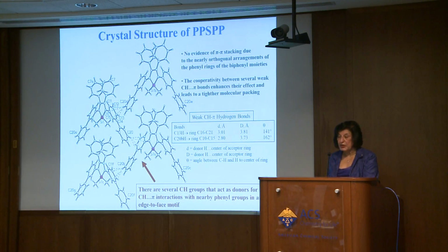So we decided to grow single crystals, and it was a big challenge, because it's very difficult to grow organic single crystals, unlike inorganic materials, which are very simple to grow. So we succeeded in growing one, but not the other. We were not able to grow the other one. What we found was no evidence of pi-pi stacking, which would encourage electron transport, for this compound, which is the weaker of the two. So that's consistent with the picture of this compound not being as good as the other one.